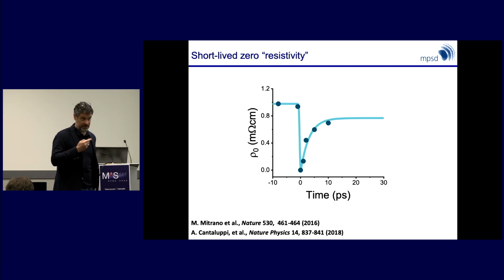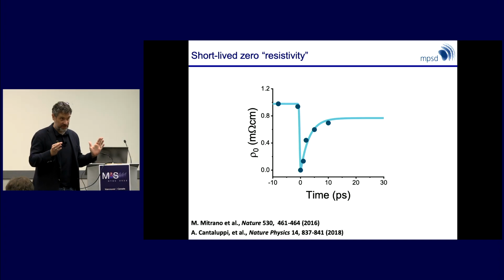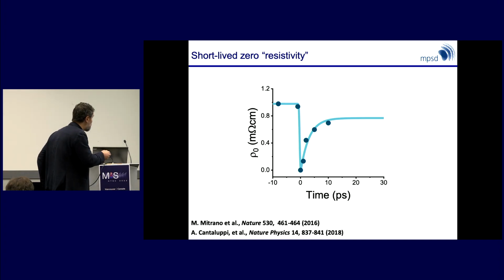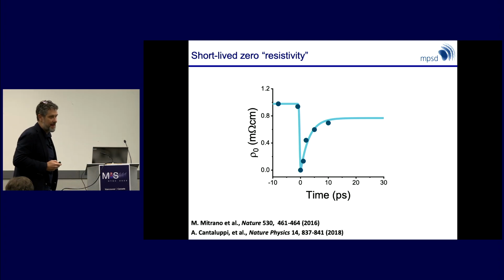And this, of course, has all sorts of problems, including the fact that once you look at this fast dynamics here, you really have to be very careful in the way you fit the data. And at some level, who cares about making a photo-induced superconductor that only lives for 1 picosecond?